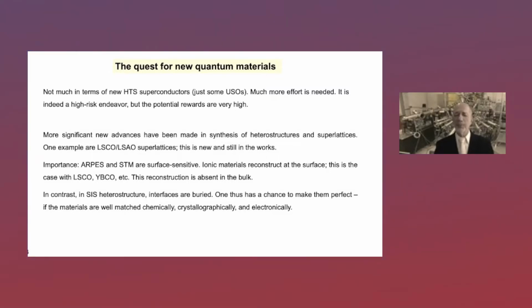ARPES and STM are surface-sensitive techniques, and we know from Material Science 101 that every ionic material will reconstruct at the surface, because the Madelung cohesion energy is long range, and the surface is seeing half of the Madelung energy from the middle of the sample. Therefore, lanthanum strontium cuprate, YBCO, etc., they all reconstruct at the surface. And this reconstruction is not seen in the bulk. So bulk is different from the surface.